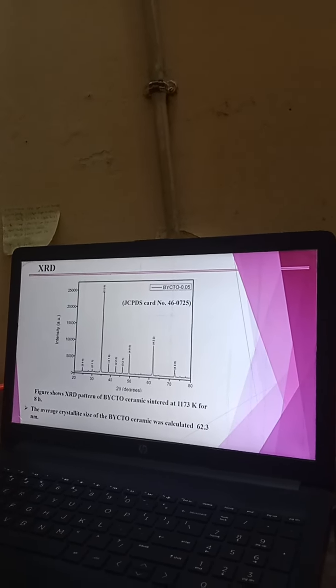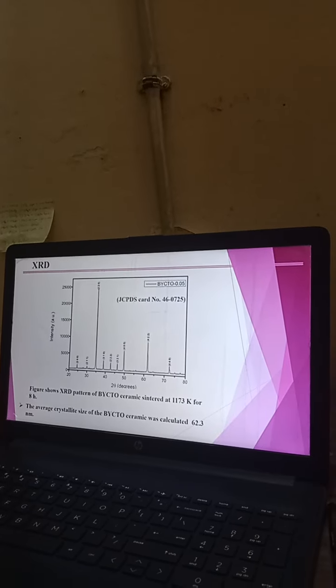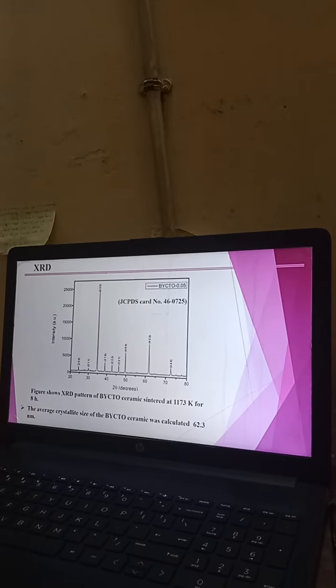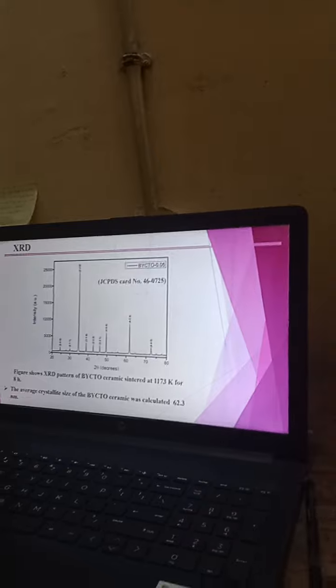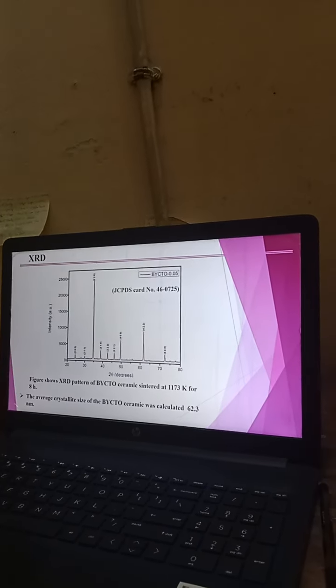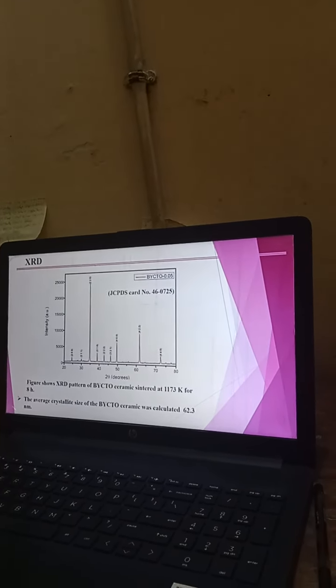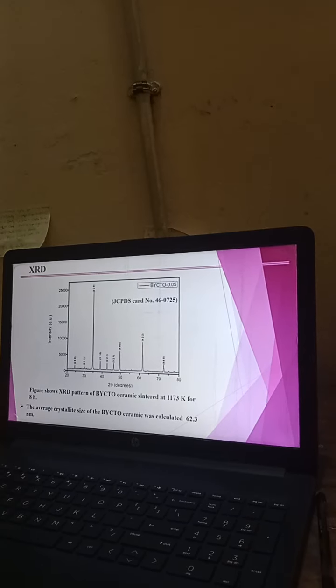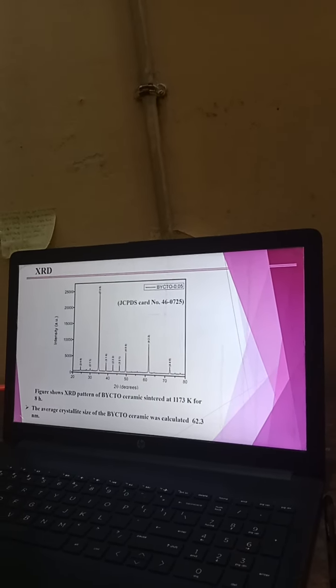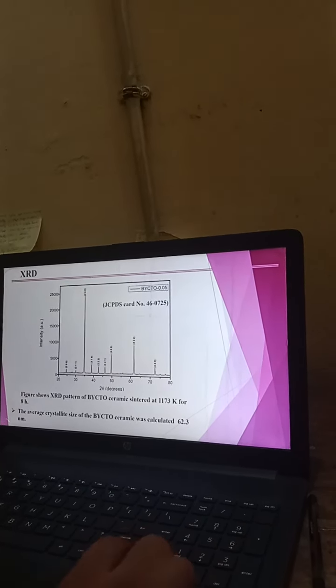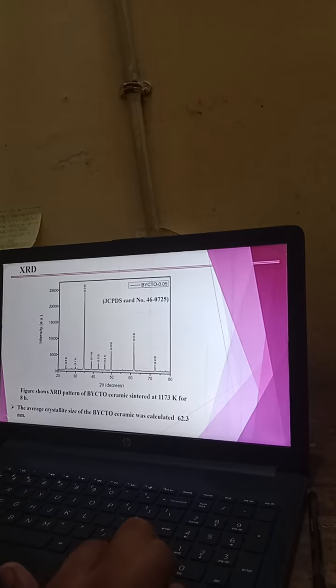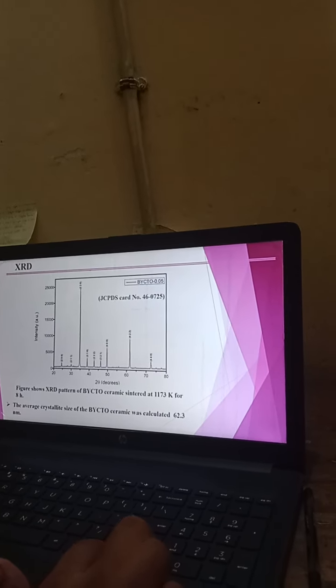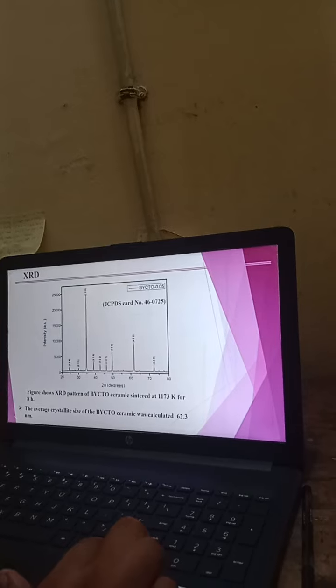In the XRD pattern, there are several peaks of different 2 theta values. In this XRD pattern, each peak has an individual crystallite size. So the average crystallite size of the BYCTO ceramic was calculated to be 62.3 nanometers.